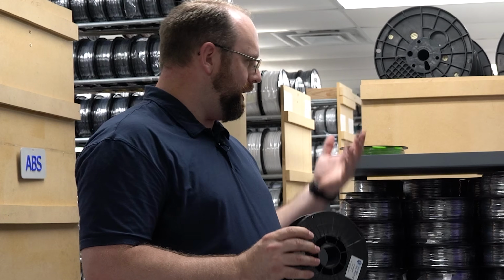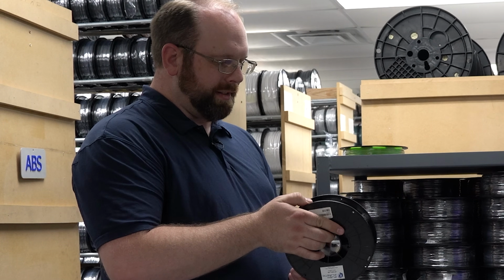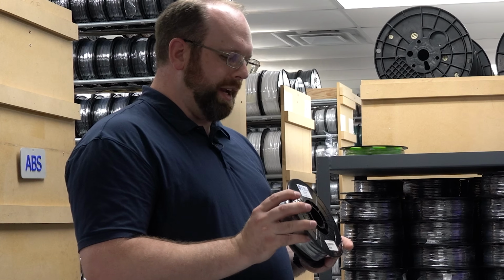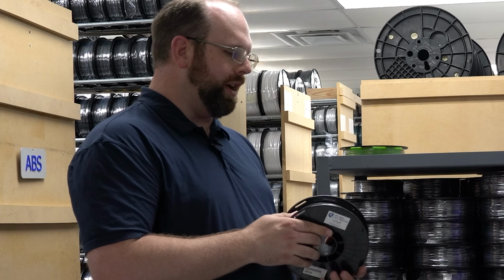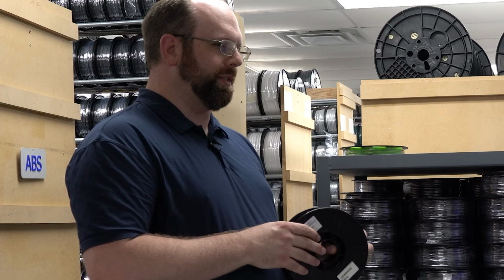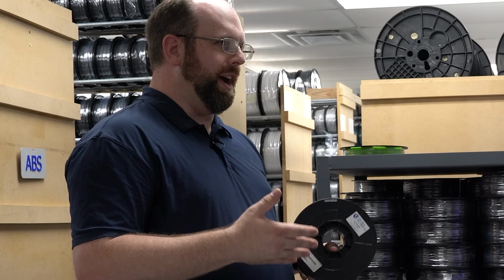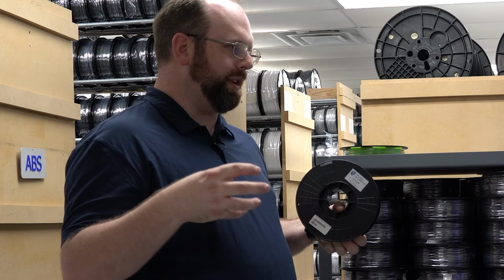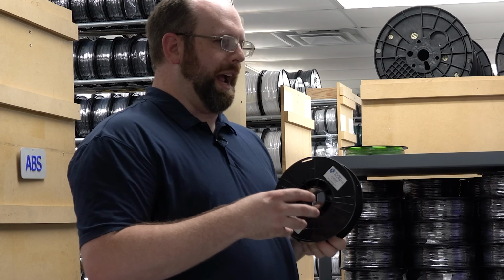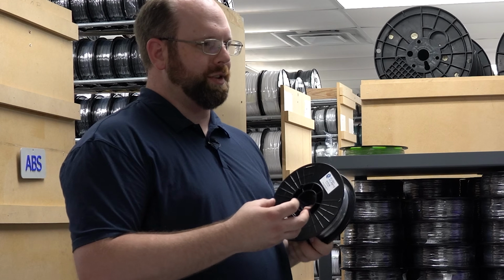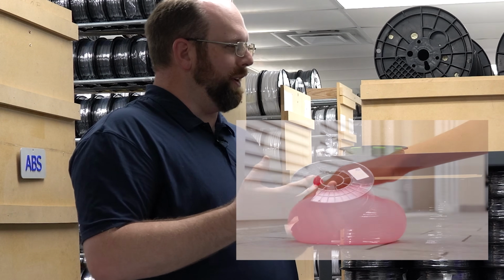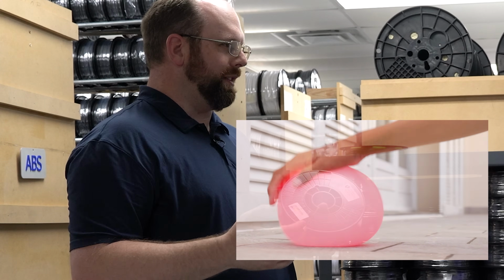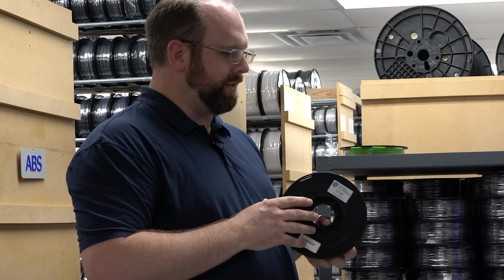Yeah, so the difference between nylon and PLA is that what you're experiencing isn't hydrolysis. It's kind of like a sponge. Due to the way these molecules fit together, they like to have water in between them. It's well known that nylon really likes to absorb moisture, also called being hygroscopic. But the damage that happens is a physical deformation, not a chemical destruction. Nylon will actually swell up like a water balloon if you put it in water for a long period of time. That's why they don't use it for water-contact gears or anything like that. They use other plastics instead.